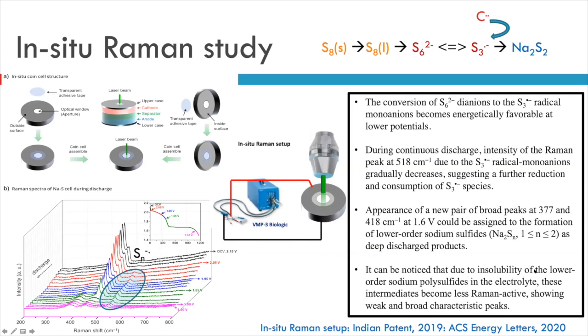We have done this because you need to see the radical formations in an in situ format. So we looked at what experiment we can do, available in our lab. And we see that Raman is one of the sensitive experiments, and sulfur can be probed by Raman. So we designed a coin cell where one side, the cathode side, which is the sulfur side, has a hole, and then we used a transparent additive to keep it from reacting with the air. So this experiment was done in an in situ mode.